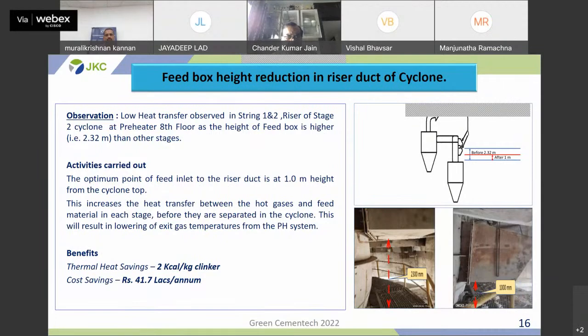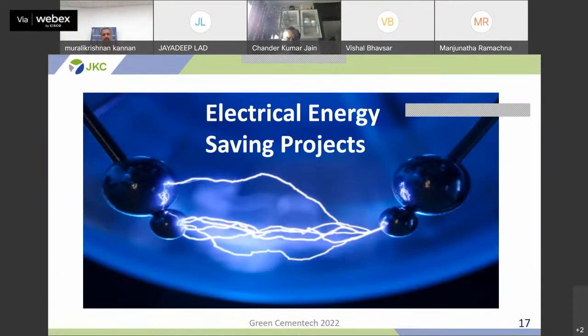The optimum point of feed inlet to riser duct is 1 meter from the cyclone top. So we have decided to reduce the feed box height by 1.32 meters. This increases the heat transfer between hot gases and raw material in each stage before they get separated in cyclones. This resulted in lowering exit gas temperature in preheater systems. By this, we have achieved thermal saving of 2 kilocalories per kg clinker and cost savings of around 41 lakhs per annum. We always convert spark of possibility into flame of achievement.